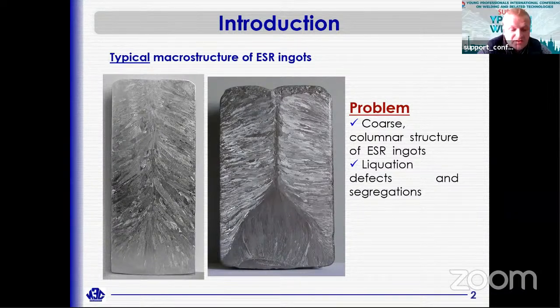Electroslag remelting is widely used for the production of ingots from a wide range of steels and alloys. But ESR ingots have disadvantages. They are shown on this slide. It's the coarse columnar structure of ESR ingots and liquation defects and segregation. That is why it's necessary to develop methods of influence on the crystallization of the ESR process to improve the structure and chemical homogeneity of the metal and suppress the liquation processes.